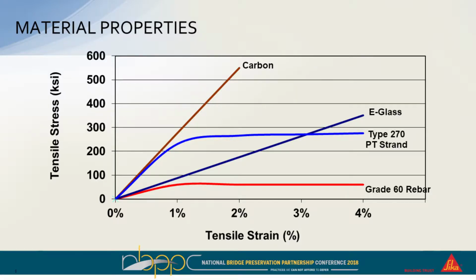Kind of a rule of thumb, it's not exactly the case, but you can think, especially with carbon fiber, they're about, say, 4 to 5 times stronger than conventional steel, but they're about 1/4 to 1/5 the weight. So that strength to weight ratio is really one of its biggest attributes in addition to the corrosion resistance.